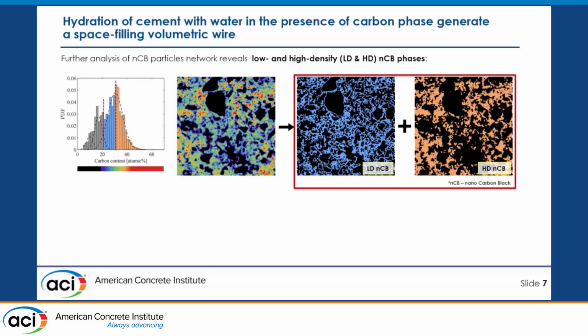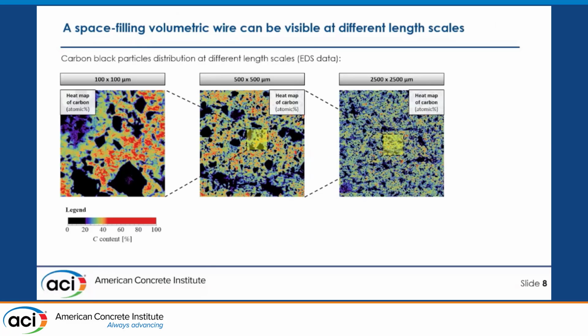Using further analysis, we could distinguish between low and high density, or more precisely low and high concentration nanocarbon network, which is basically phase of nanocarbon particles intermixed with hydration products, CSH, Portlandite, and so on. What is also remarkable is that this space filling volumetric wire is present at different length scales, showing us a fractal dimension.